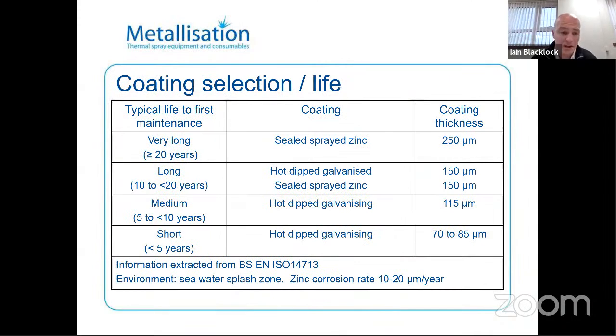A bit of information on coating selection. This is taken from the British Standard 14713. So you can see that the territory that we're in is long-term corrosion protection. It's showing the hot dip galvanizing, which tends to be thinner film. But then we get up to hot dip galvanizing 150 microns versus sealed sprayed zinc. To get the 150 microns of galvanized, there's certain things that you have to do with the process, so it's not just your standard dipping process as Martin described earlier. And then going above it, 250 microns of sealed sprayed zinc. The sealer coatings will cover it shortly to give us the very long life of corrosion protection as seen here.